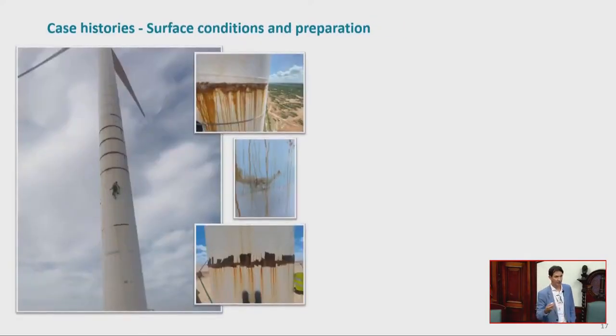So we thought, okay, how do other coatings perform, while they have passed the corrosion at scribe test, in reality? And this is what we see, because this is actually what we repair. So here is the kind of paradox where a non-ISO certified coating is repairing ISO certified coatings. But you know, this is reality and this is what we see. Now, what happened here? Why did we get these failures? We know we passed the test.